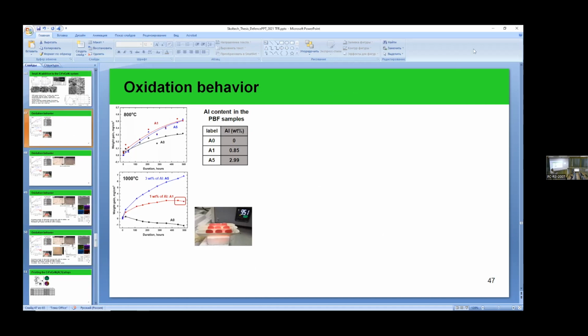So here you have presented 2 graphs, at 1000 degrees Celsius and 800 degrees Celsius. I see at 1000 you see delamination, right? But at 800, I suppose you don't see any delamination. Yes, exactly. For the materials with alumina, we didn't observe this delamination, but you see that this weight gain is quite small. In case of 1000, it was clearly observed for the material without alumina. And on the last stage of the materials with small alumina content, we observed this delamination.